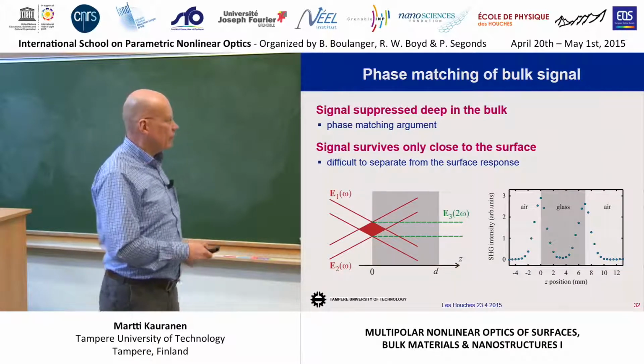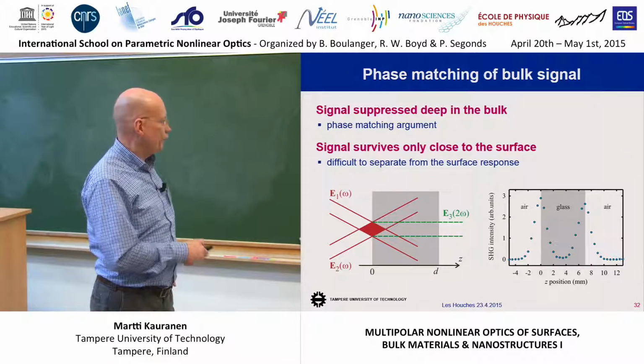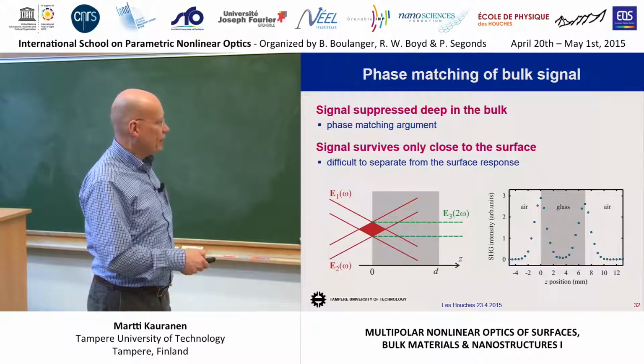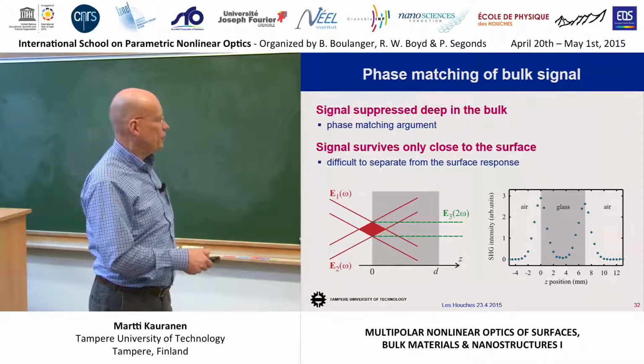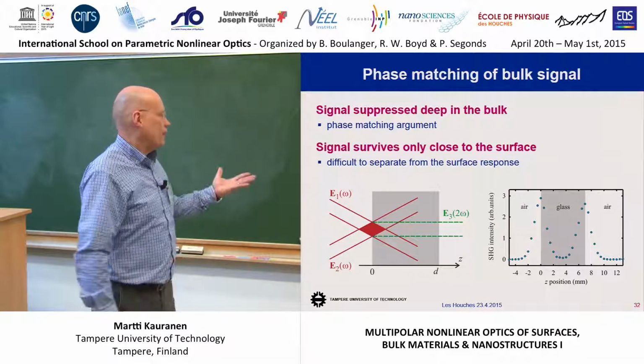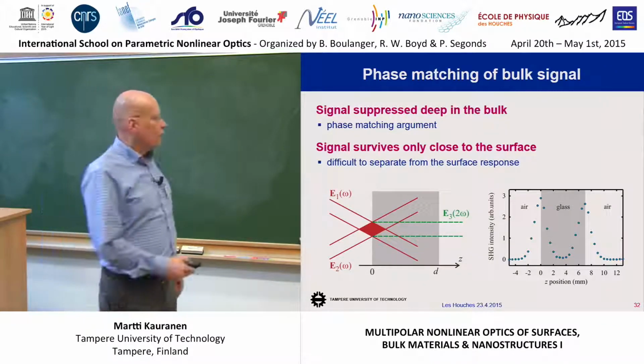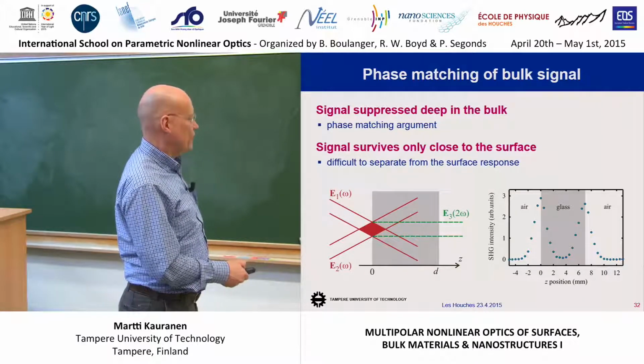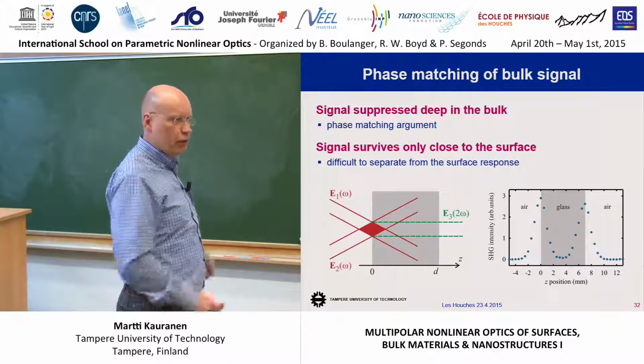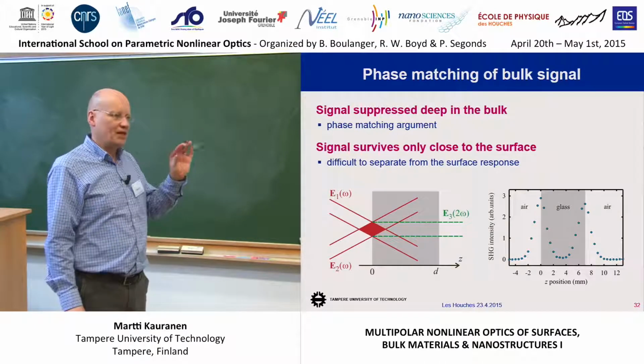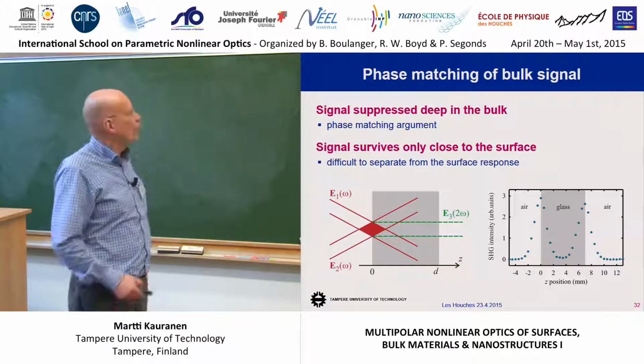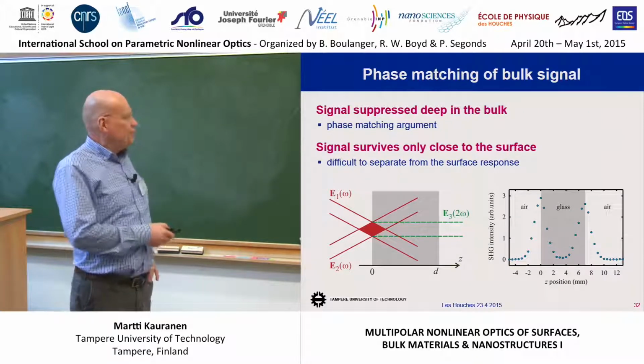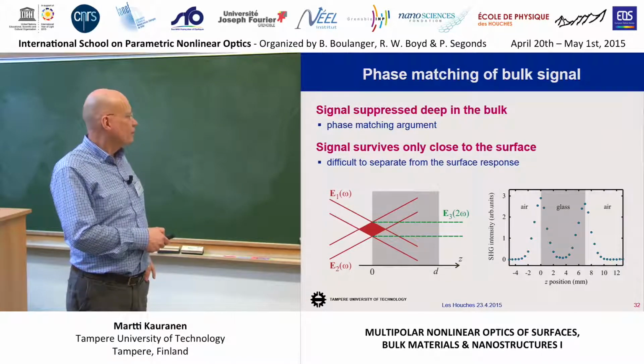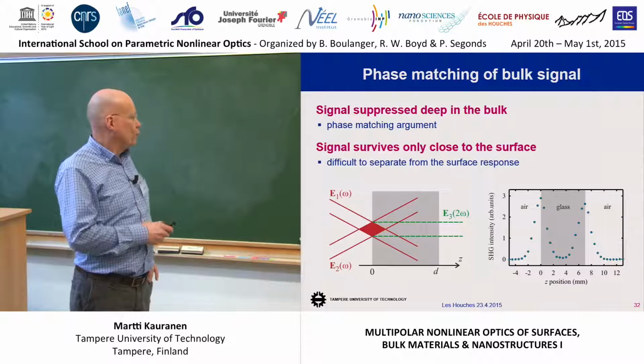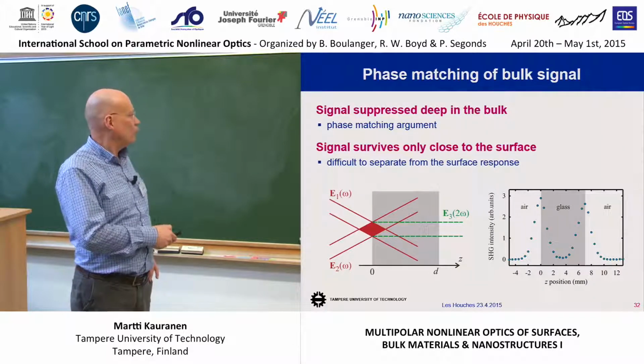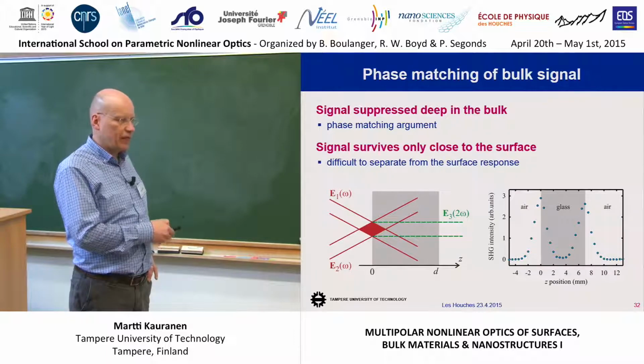And we verify this in an experiment. So we scan the sample through this interaction region. We get something at the, let's say, glass-air interface, and then again something at the glass-air interface. Of course, if you look at this, you might say that this must be a surface response. But a surface response does not extend millimeters into the material. A surface response is localized into a very thin surface layer. But the problem is that when we try to measure this bulk response, we are going to be interacting also with the surface response at the same time. So that's a complication.